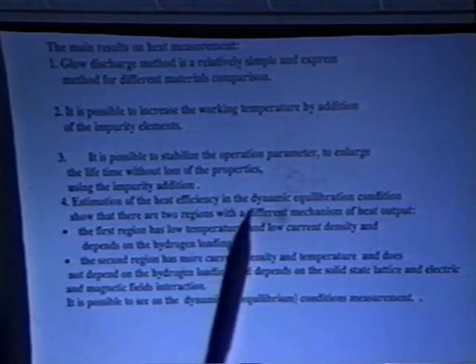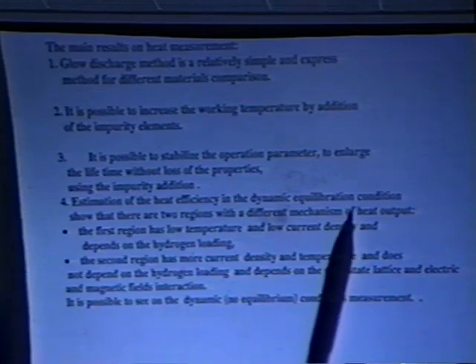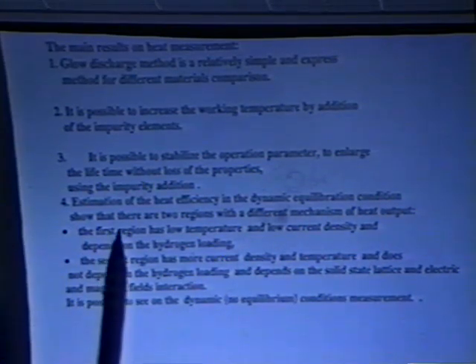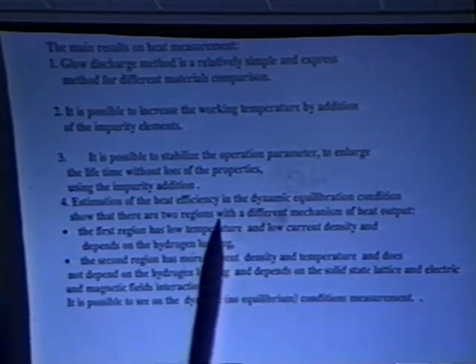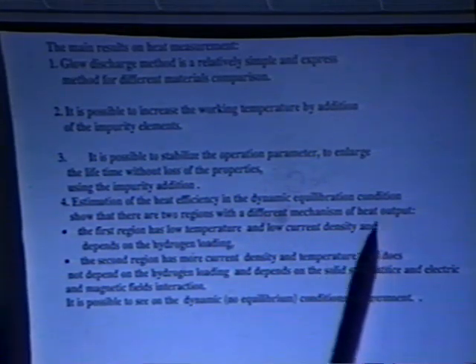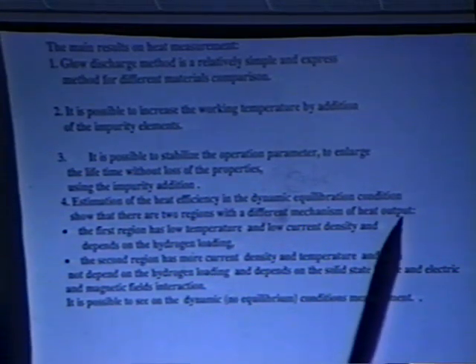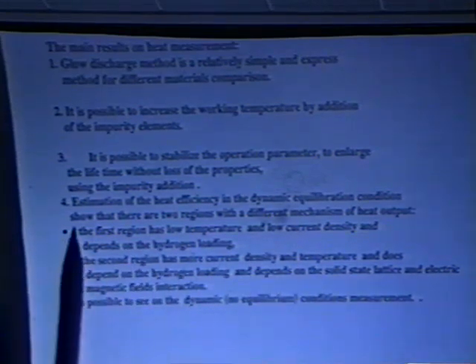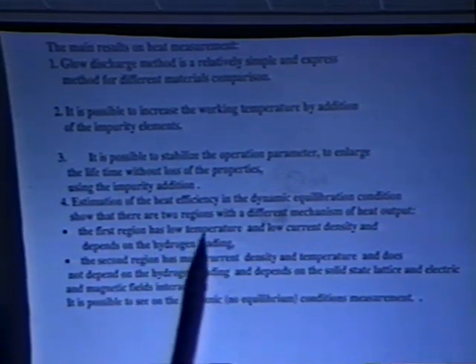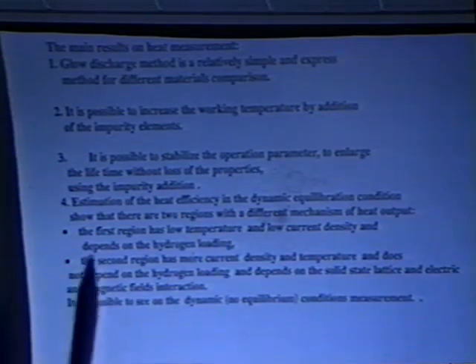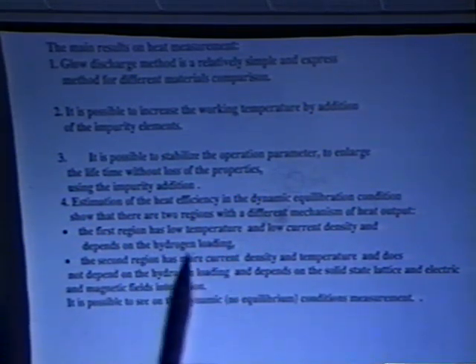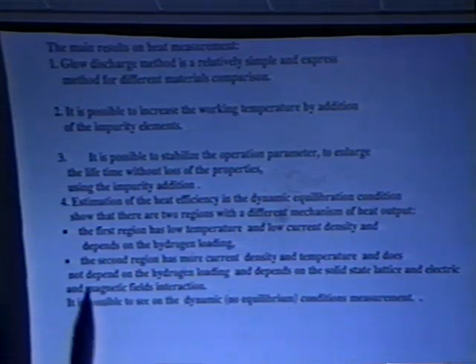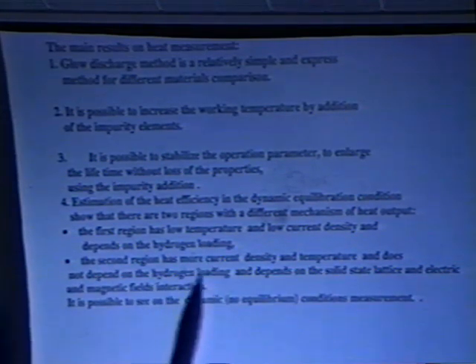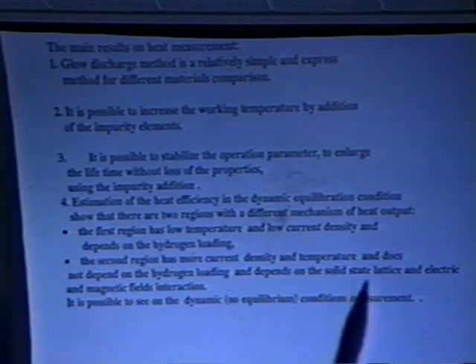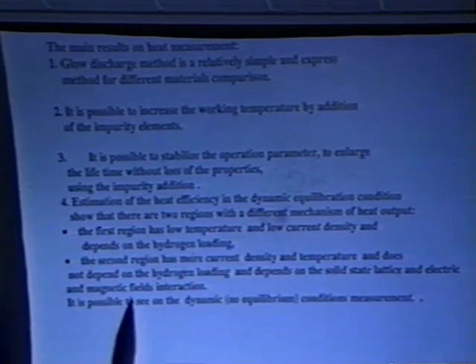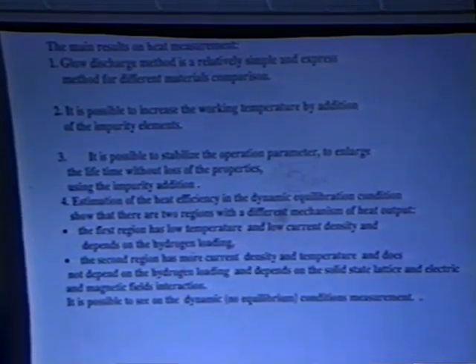Estimation of the heat efficiency in the dynamic equilibration condition shows that there are two regions with different mechanisms of the heat output. The first region has low temperature and low current density and depends on the hydrogen loading. The second region has higher current density and temperature, and does not depend on the loading.